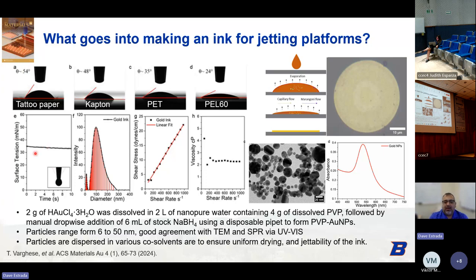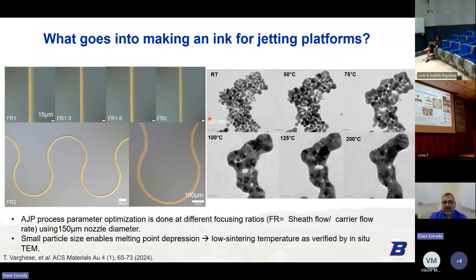Here's an example where we measure surface tension for this, and we see our particle size in solution is about 100 nanometers. So we're getting some agglomeration, but the shear stress versus shear rate is linear, and viscosity is constant over shear rate, showing we have good Newtonian behavior of our ink. Our co-solvent system is also designed to induce Marangoni flow and convective currents as the ink dries, so we end up with a nice uniform film of gold instead of gold at the meniscus edge and a coffee ring effect. And then we look at the interactions with different substrates like tattoo paper, polyimide, PET, and PEL60, to show that we have good wettability across a variety of surfaces with this ink.